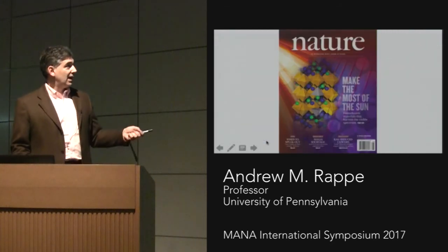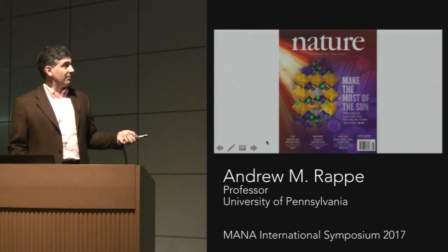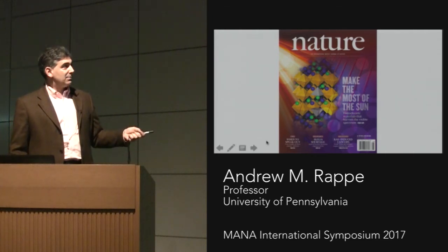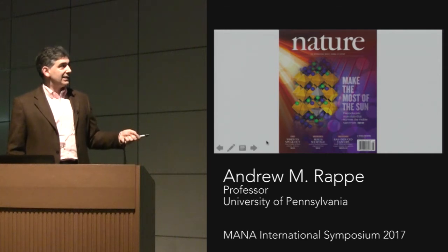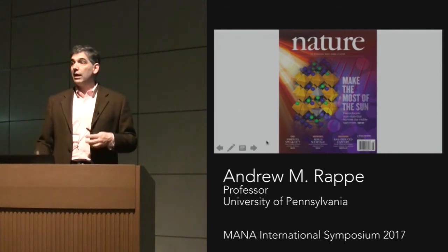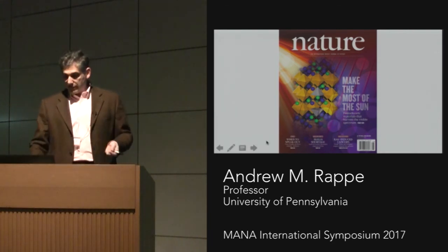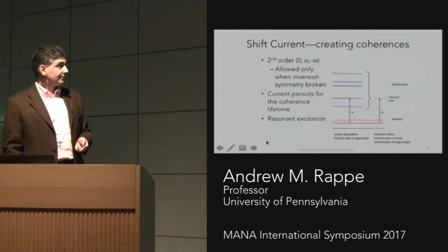Okay, and this is a large image of this alloy material, and the idea is that the niobiums have complete octahedral cages, but the nickel ions bind a vacancy, and so their cages look incomplete, and it's this nickel vacancy complex that provides states in the gap to provide visible light absorption.